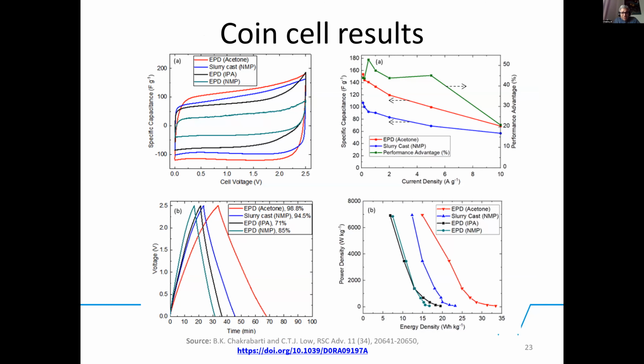So here are the other coin cell results. Cyclic voltammetry on the extreme left-hand side, the top side, compares the different electrolytes for the EPD process against the standard slurry cast method, showing that the acetone solvent with the iodine as the charging agent for the activated carbon particles for controlled migration, as well as PVDF as the binder, gives the highest capacitance at 20 millivolts per second.